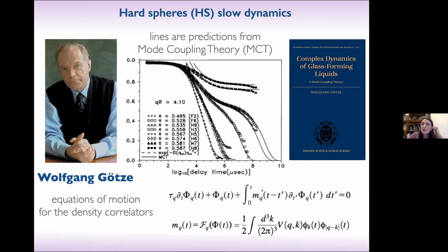The crucial approximation of the theory is the choice of this memory kernel. Mode coupling theory writes this memory kernel as a functional of the density autocorrelation function, so that you have it here and you can solve these equations. This functional is an integral which couples different modes, by which the theory takes its name, mode coupling, by means of static coefficients. The important thing is that when you know these coefficients, which only depend on the static structure factor and on the number density of the system, you can calculate the full decay of the density correlator. This is what Van Megen did in his paper.